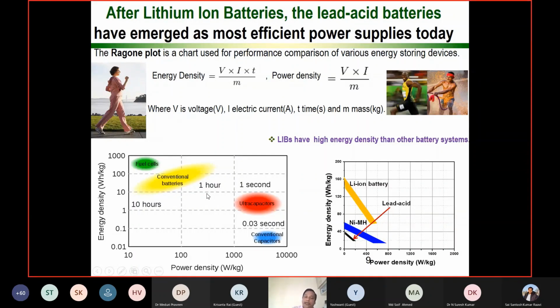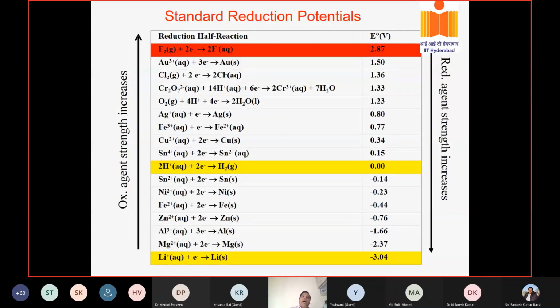So lithium-ion batteries have an energy density of about 150 to 200. Sorry, now it's more than 200 watt-hour per kilogram, but it's like 150 to 250 watt-hour per kilogram. Whereas the lead-acid battery has a very, very poor energy density. This is just 30 to 40 watt-hour per kilogram because lead is heavy. I'll come to that actually. So before going to today's cells and batteries, I just wanted to give you a flavor of how you make electrochemical cells.